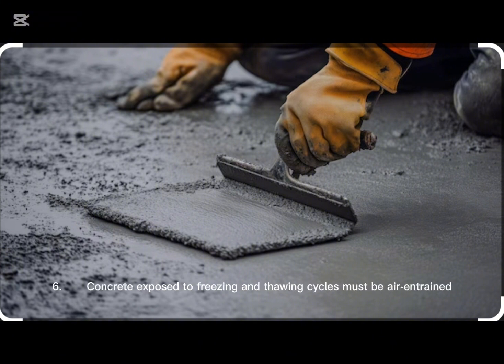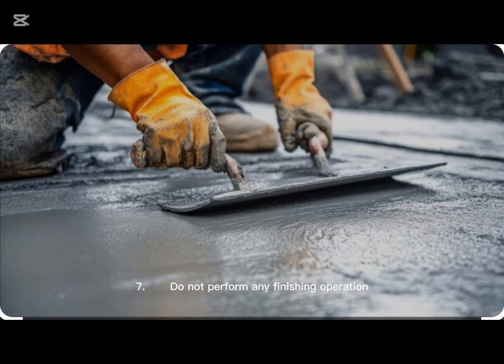6. Concrete exposed to freezing and thawing cycles must be air-entrained. 7. Do not perform any finishing operation with water present on the surface, and also initial screeding should be done followed by bullfloating. 8. Properly slope the concrete surface to drain water away from the slab. 9. Provide proper curing by using a liquid membrane, curing compound, or by covering the surface of the newly placed slab with wet burlap.